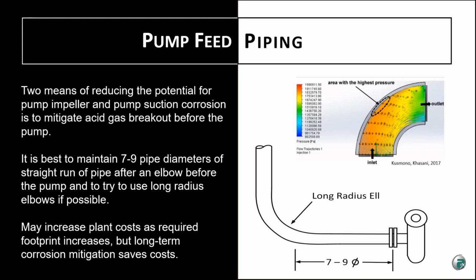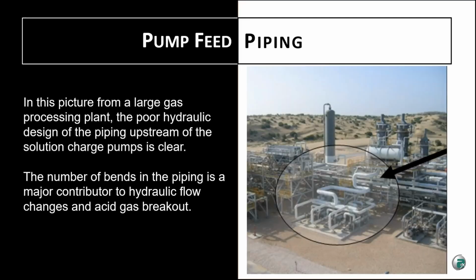If you see corrosion on the inner diameter of the elbow, it's generally related to acid gas breakout because of the lower pressure drop conditions at that location in the pipe. So if you have corrosion on the outer elbow, it means you've got erosion corrosion, and if the inner part of the elbow is damaged, it's generally related to acid gas breakout from hydraulic flow effects.